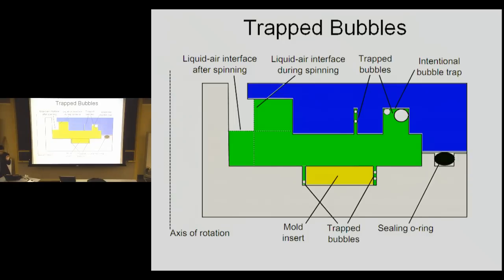That's a good question. Maybe I can make sure I understand. What you're saying is that some of the bubbles could go into solution, and some will not necessarily go into solution. We're just interested in looking at the growth of some of the bubbles. It depends on their initial size. It is possible that some could have gotten very, very small and then started to evolve again. I agree. So at the limit of our detection, we selected a few bubbles that were in some type of transient state. They were already growing, and we wanted to map out their continual growth. Maybe some of these bubbles were very small at some period of time, but we can only see them a little bit later.